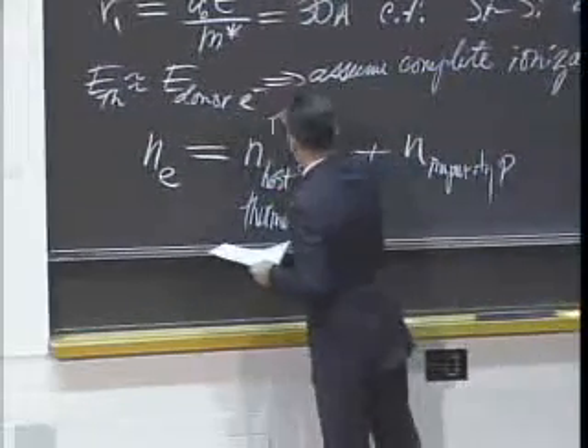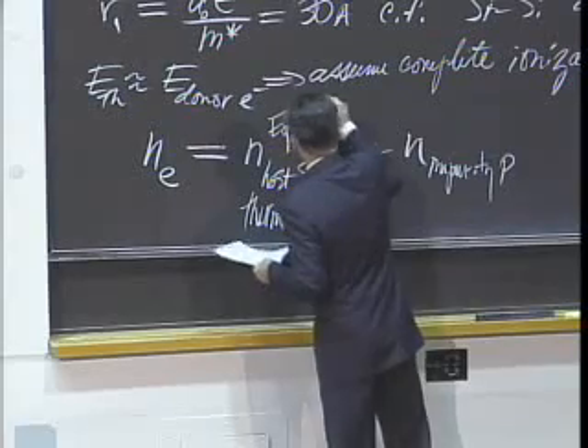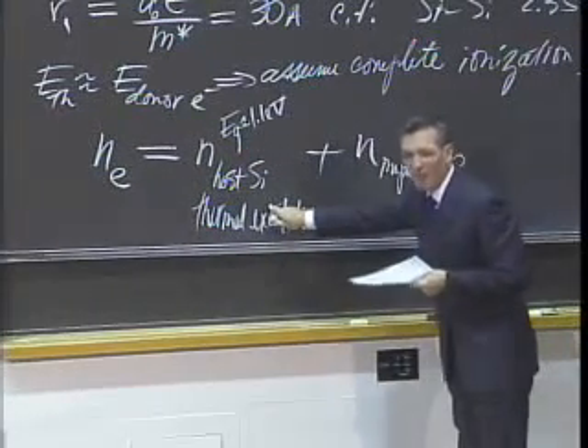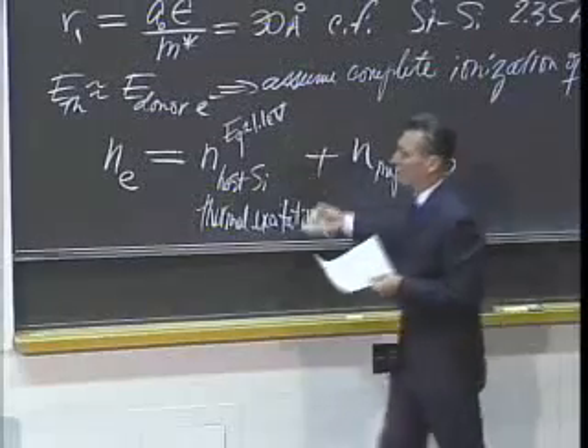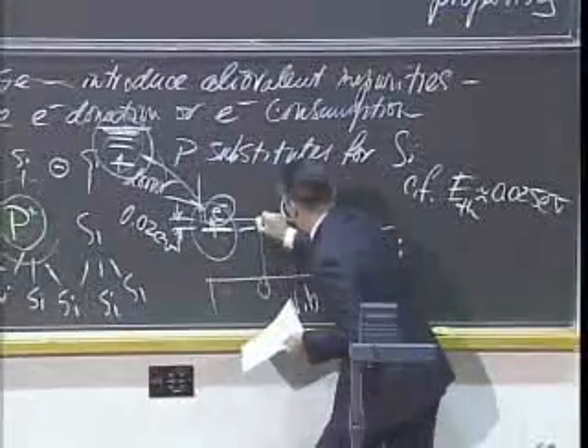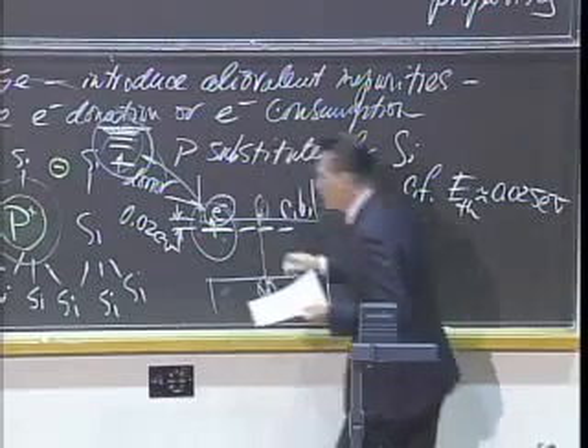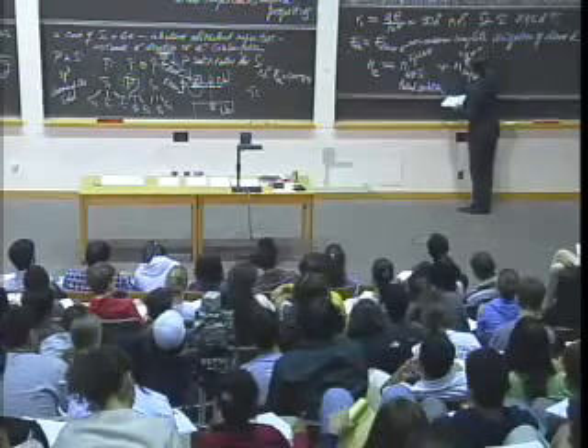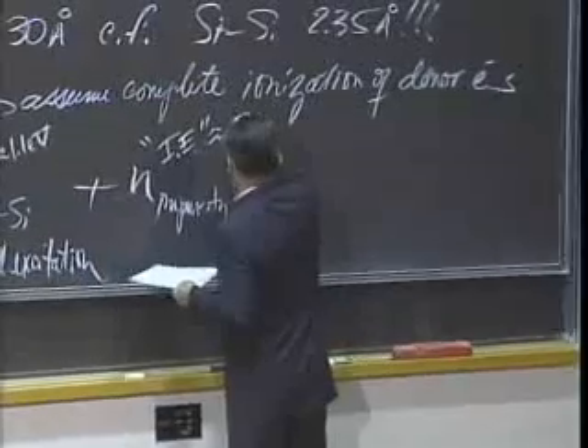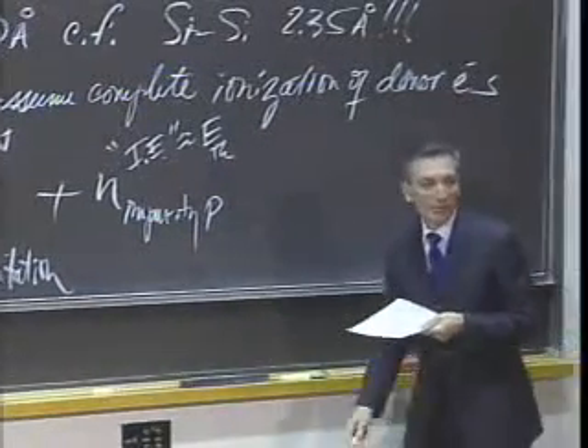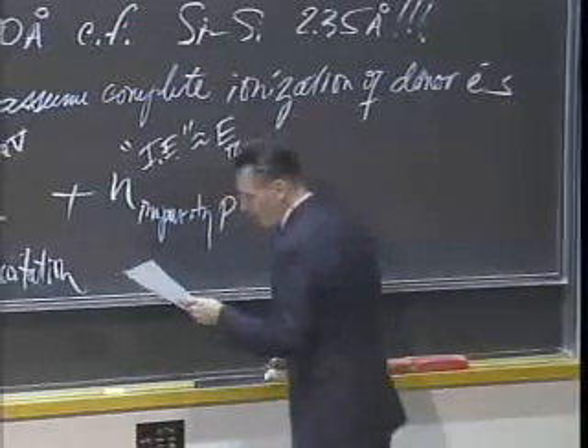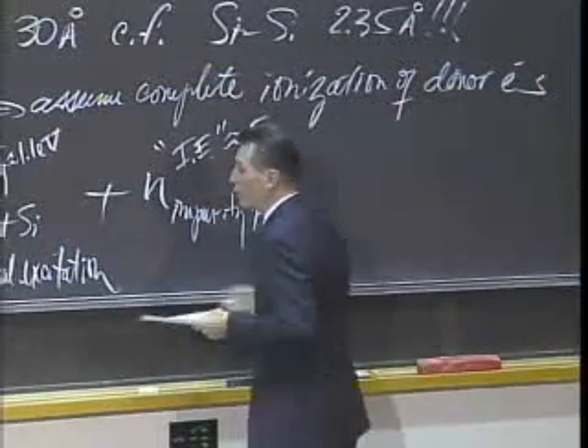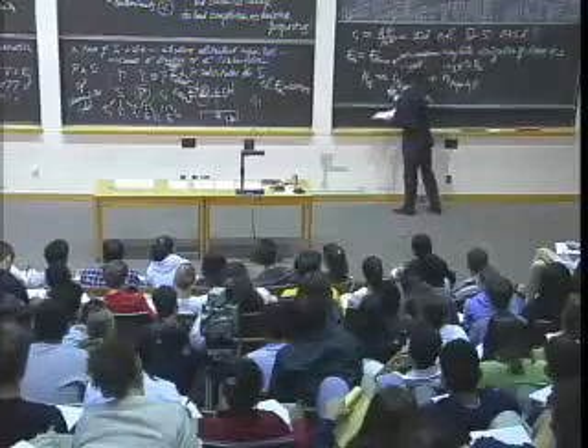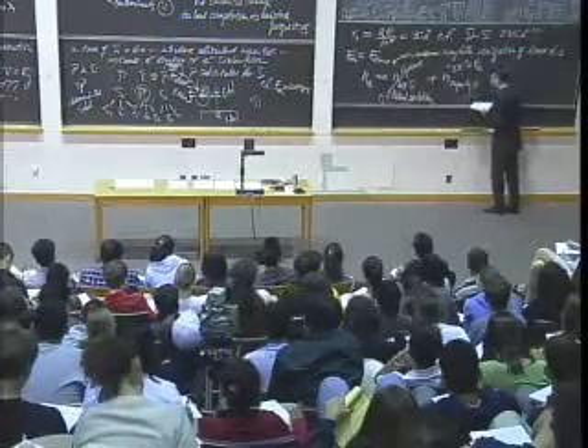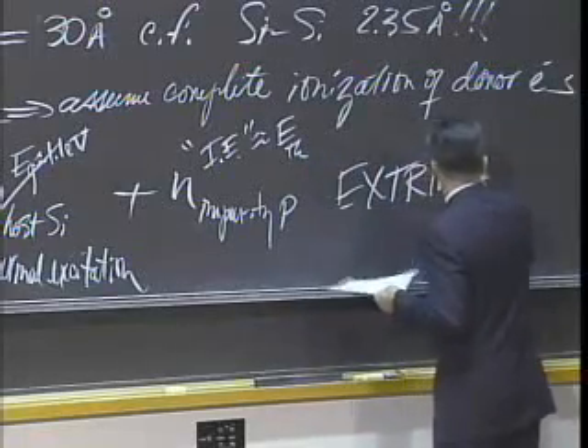And we know this requires Eg on the order of about 1.1 eV, so very few of these are contributed. There's almost no promotion of electrons from the valence band to the conduction band to leave holes. This is vanishingly small at room temperature in silicon. Whereas here, because I'm going to put in quotation marks, the ionization energy is on the order of the thermal energy, we get all the electrons from here. And so in such a material, we say that the electrical properties are essentially those from the impurity. So we send this to 0, and we say that such a material exhibits extrinsic behavior.